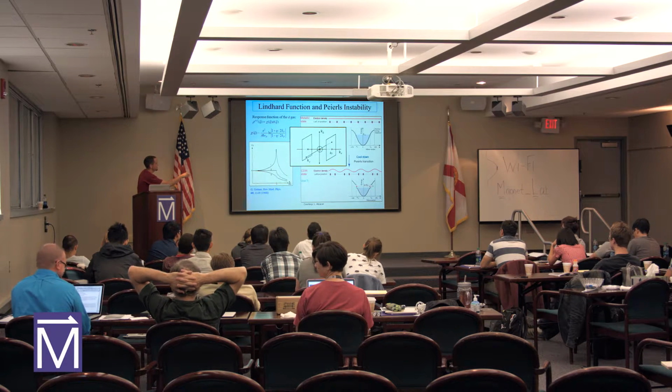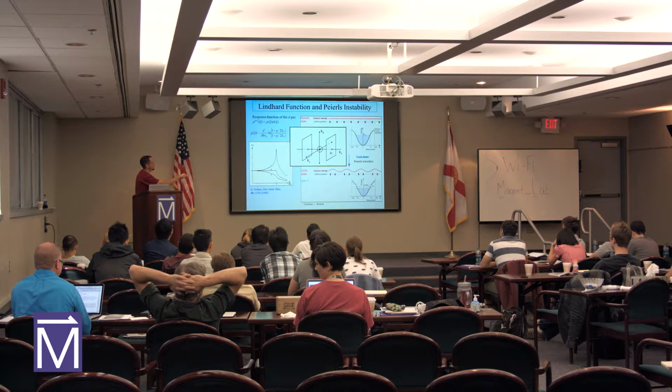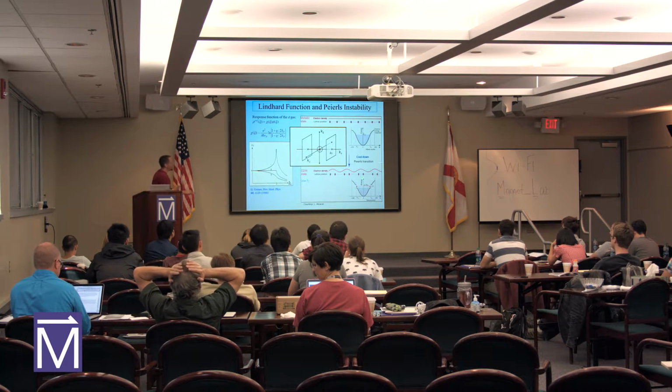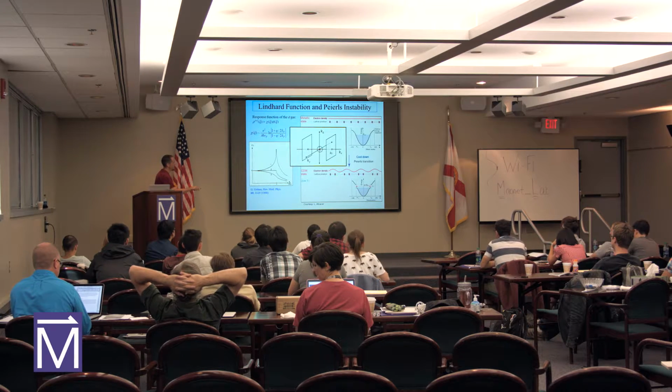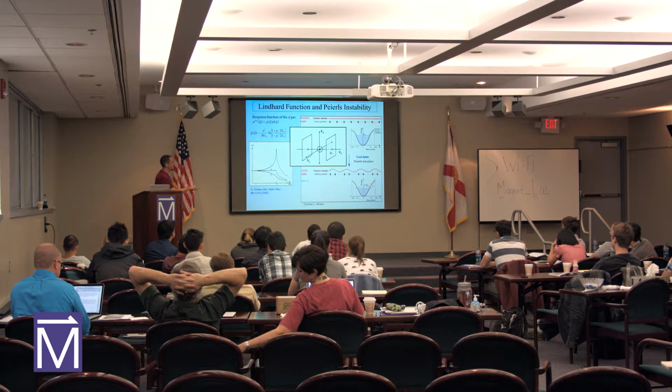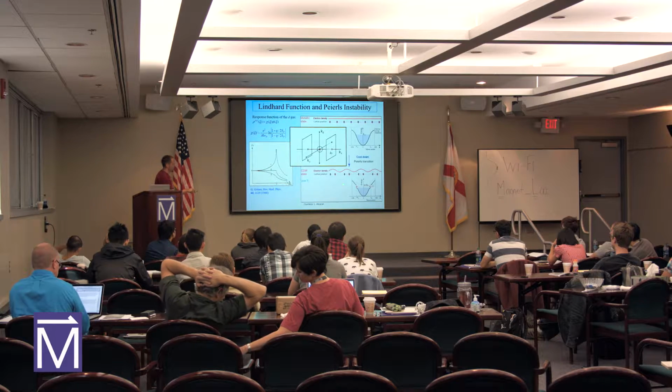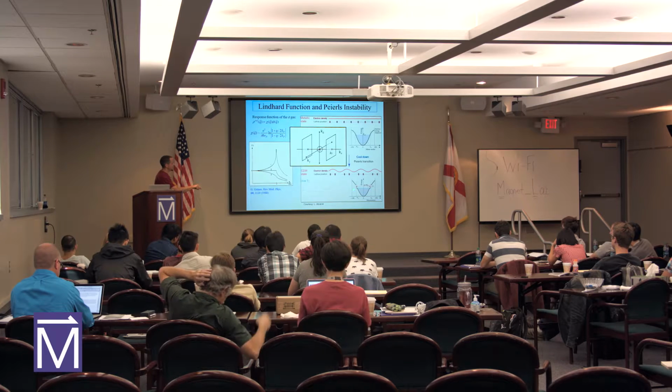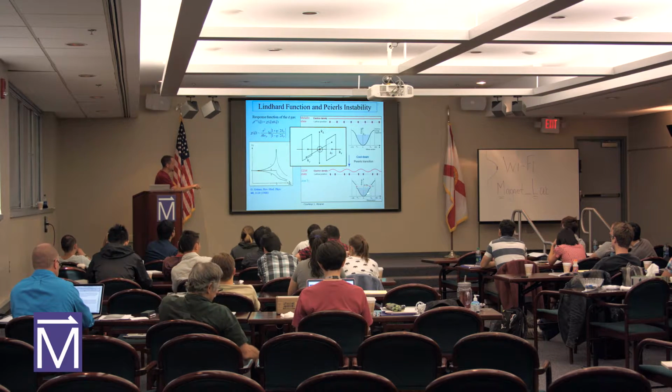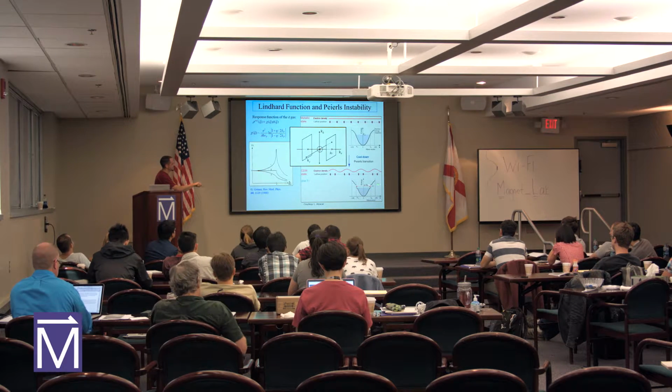We have a metallic state at room temperature. So we have equally spaced lattice points, a uniform electron density, and a partially filled band. It's a metal. Now when we cool it down, we get some energy gain from shifting points of the lattice closer together. They start to form pairs, or dimers. It costs energy to move the lattice around, but there's a gain because the overall electronic energy is lowered, since a gap begins to form as the lattice shifts.